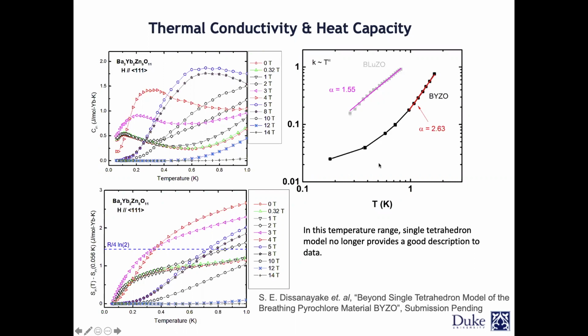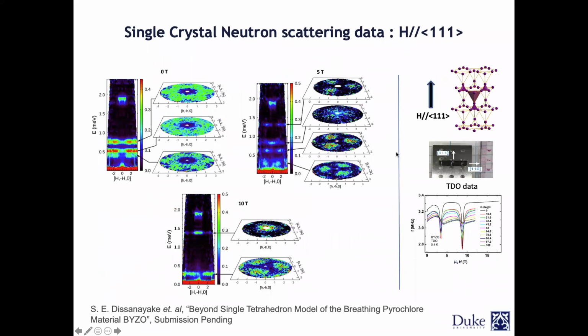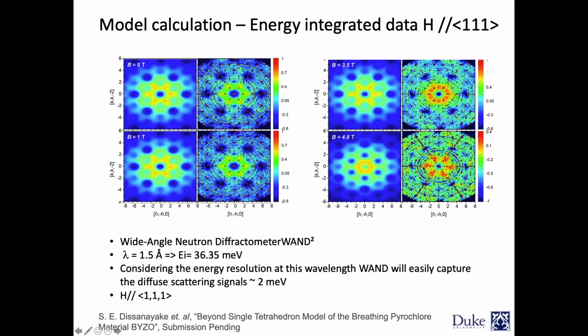Now there is something else that we are going to add in: the neutron scattering data. With the neutron scattering data, if we look at 0 Tesla, 1 Tesla, 3.5 and 4.8, for 0 Tesla there is an agreement, and for 1 Tesla as well, between the theory and the neutron scattering data. So you're looking at all energy integrated down to lowest energy and Q. And this is the theoretical work for it. You can see that they are in good agreement. At 1, they are also in good agreement. 3.5 is where it starts to deviate from the theoretical work, and at 4.8 it is completely different.